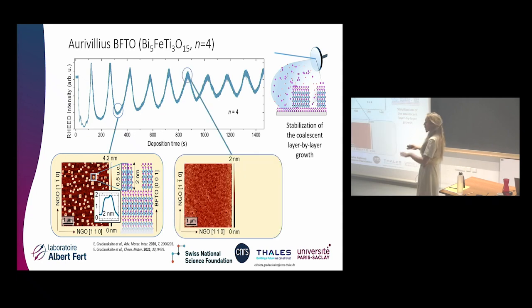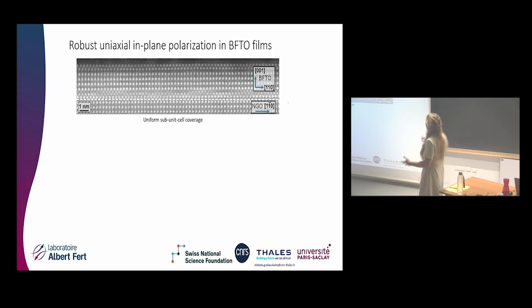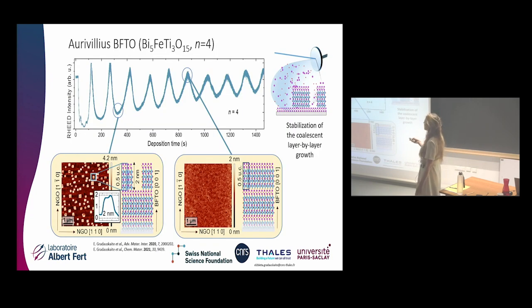So in fact, we don't grow layer by layer of perovskites. We grow full electrostatically neutral units, and then they coalesce to form very nice films. So it means that we can now control our thickness with the precision of half unit cells. So we can indeed grow something that's completely flat and only half a unit cell in thickness of these layered materials. In fact, maybe did I forget to tell you the composition? What I'm working with here is BFTO. So it's bismuth 5, iron, titanium 3, oxygen 15. So it's a layered material that has 4 perovskites and then this bismuth interplane. So that's the material I'll be talking about.